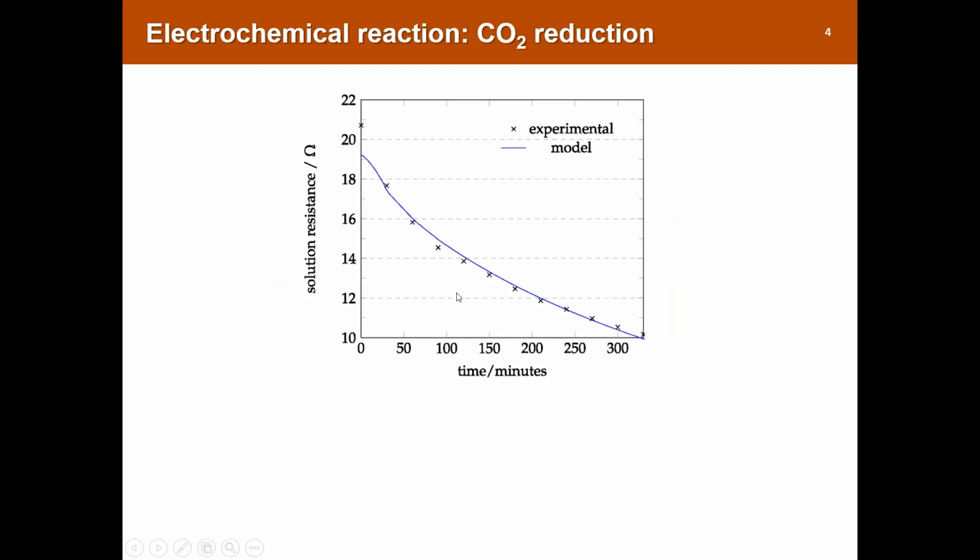And another characteristic of the CO2 reduction system is that as we run the electrochemical testing, the solution resistance does decrease. So that means the RU value decreases, so the IR compensation value should change. But if we do the impedance analysis first before measuring the performance and do the positive feedback mode, we cannot reflect how the RU changes because we put in the initial RU value, but we didn't know what RU value actually exists in the electrochemical system.